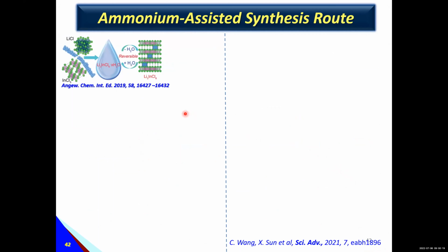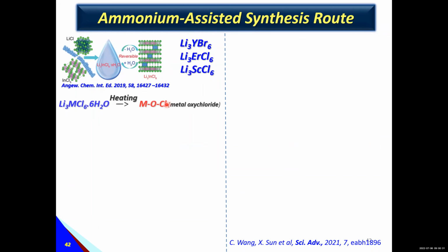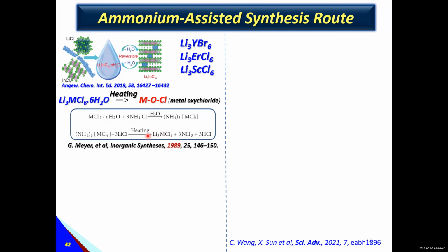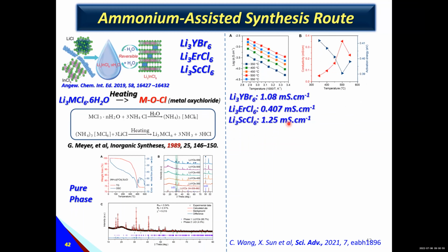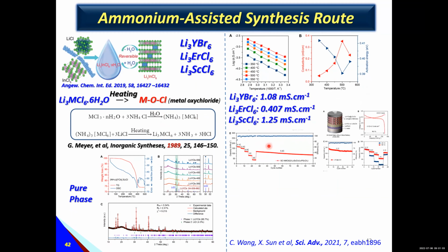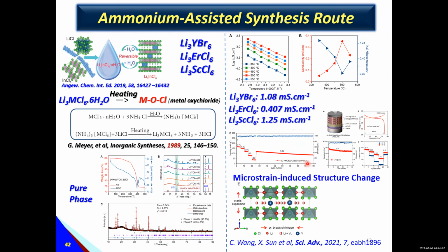Recently, we worked on another approach. The reason is that lithium indium chloride works using a very simple process, but we cannot synthesize other systems. The reason is when we synthesize other systems using the simple liquid method, they have impurities. Those impurities decrease ionic conductivity. And then we found how to remove these impurities with ammonia treatment. Finally, we can synthesize a lot of systems using this solution method with ammonia treatment. We can demonstrate the battery performance. Also, we understand the reason is related to microstrain in the structure, resulting in very high ionic conductivity.